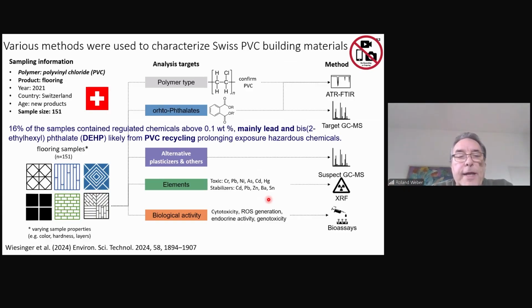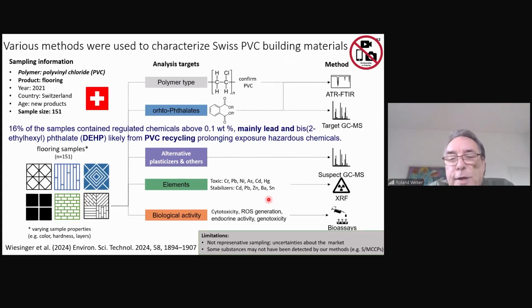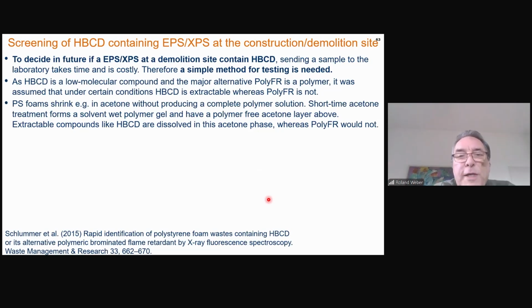flooring samples. And they found that 16% of the samples contained regulated chemicals above 0.1%, mainly lead and phthalates, this DEHP. They concluded this most probably comes from PVC recycling from older PVC where high amounts of lead and DEHP were used. Unfortunately, in that study, they did not analyze the short and medium chain chlorinated paraffins because that analysis is quite complex, and at the ETH at that time, this analysis was not available. So for Tunisia, that would be an interesting study. You could look at your PVC floorings and what kind of additives are there.